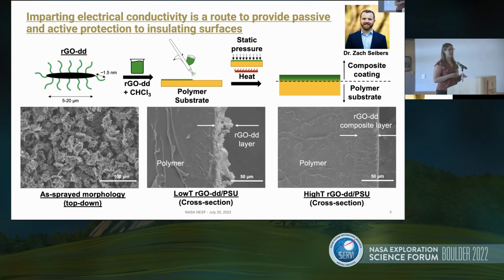And so what you can see in the center image is what happens if we process these at a low temperature. So for polymers, low processing temperature means high viscosities. So we expect to not get a lot of infiltration. And what you can see in the cross-sectional SEM image is that we do in fact have a polymer substrate and then a primarily uninfiltrated nanoparticle coating. As we increase the processing temperature, we get better polymer infiltration. And we actually get a very robust defect-free nanocomposite coating that is well adhered to the polymer substrate, in that it is the same set of sort of entangled polymer chains. So that's really an encouraging result.